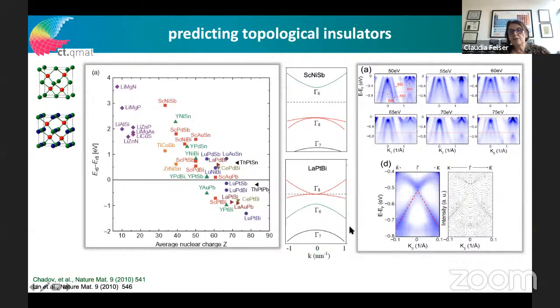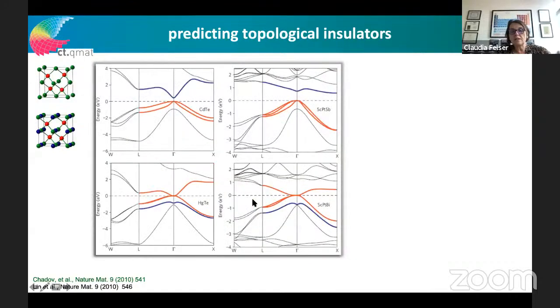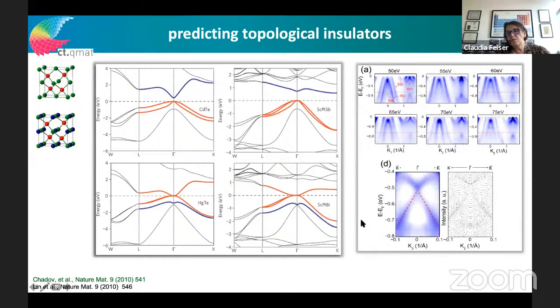They are interesting because with this ternary compound, we can also have superconductivity. So this is simply the real band structure, and it's in nice agreement - we have the surface state here, like in mercury telluride, below the Fermi energy in this ternary compound.